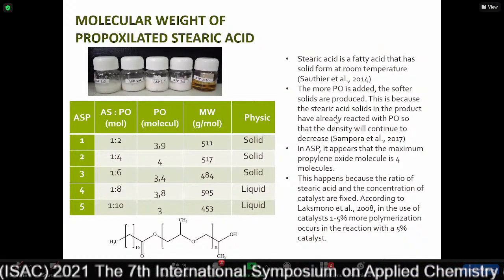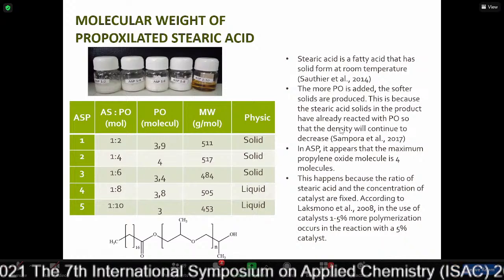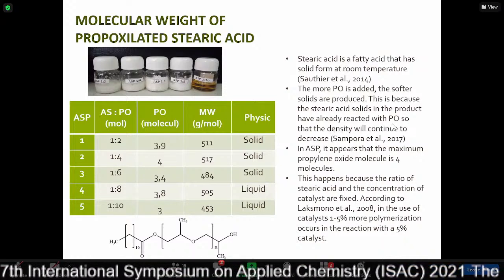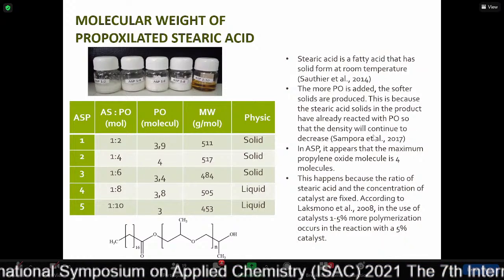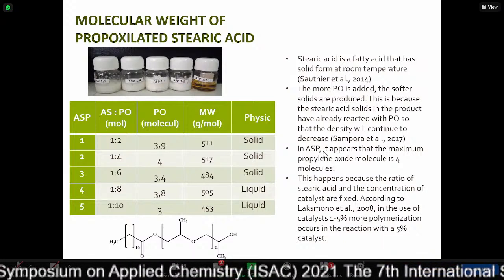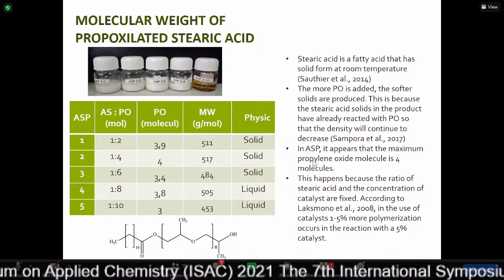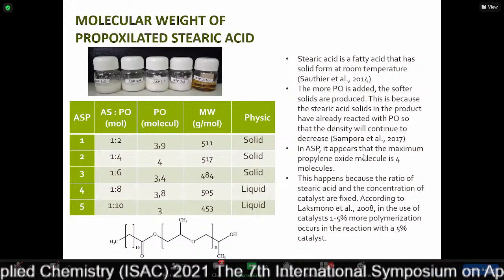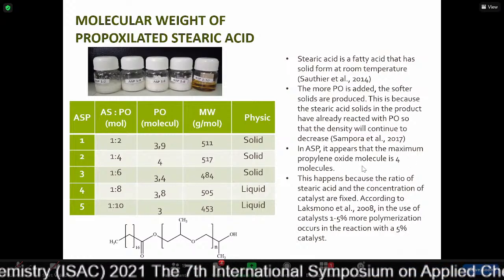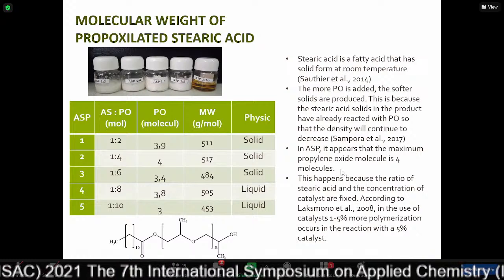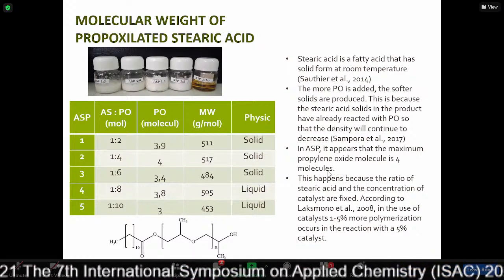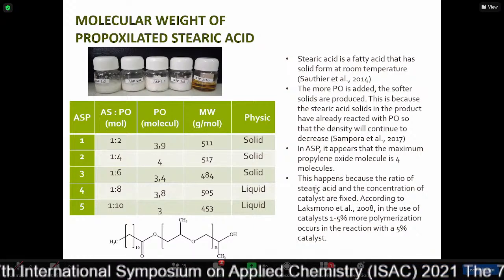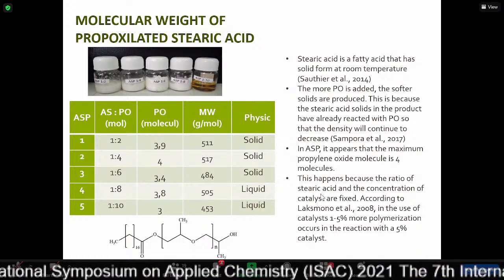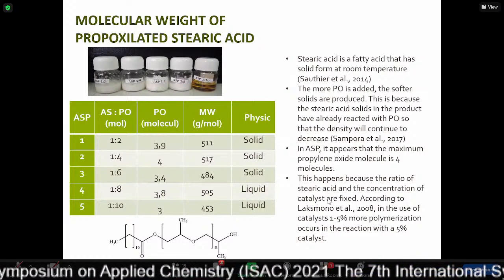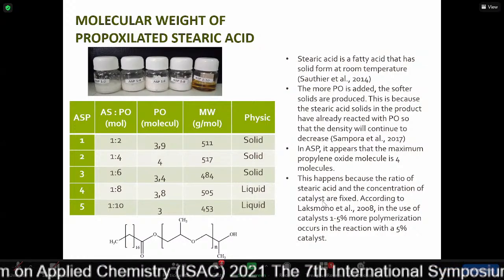This is because the stearic acid solid in the product has already reacted with the propylene oxide, so the density will continue to decrease. In this stearic acid propoxylation, it appears the maximum is 4 molecules of propylene oxide. This happened because the ratio of stearic acid and the concentration of catalyst are fixed.